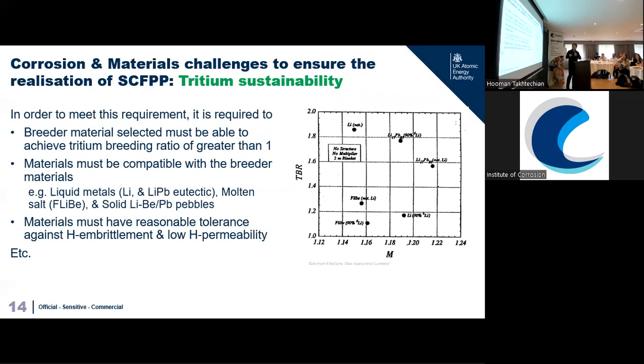So in terms of tritium sustainability, there are many options to go for, but all of them are related to lithium. So we have to find breeder materials that allow us to actively breed tritium with a tritium breeding ratio greater than 1. Because I think most of us heard this morning about hydrogen, it goes everywhere. There will be a loss in our reactor when we breed it. So we need to make sure that it's above 1 so that we cover the losses of the hydrogen, or in this case tritium, during the breeding scenario.